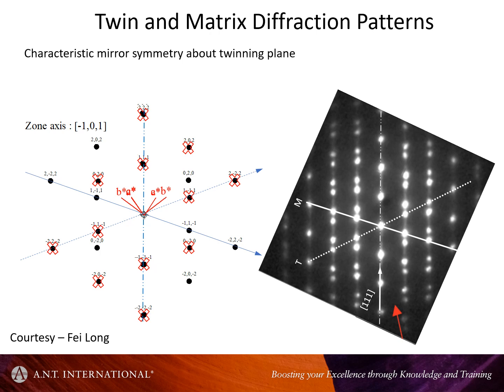But when you do have a twin, it's generally pretty obvious. You can see it in the diffraction pattern. What you see is a set of kind of double images. If we look at one systematic row of diffraction spots, which would be perpendicular to the twin plane, we have a mirror image on either side of this systematic row.